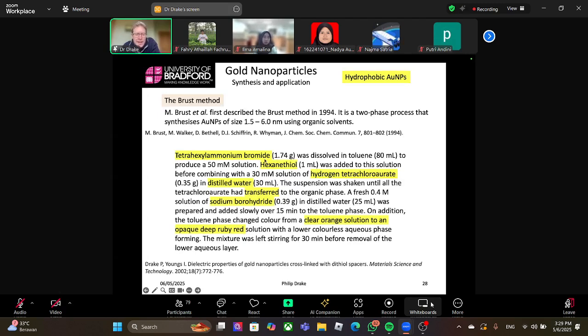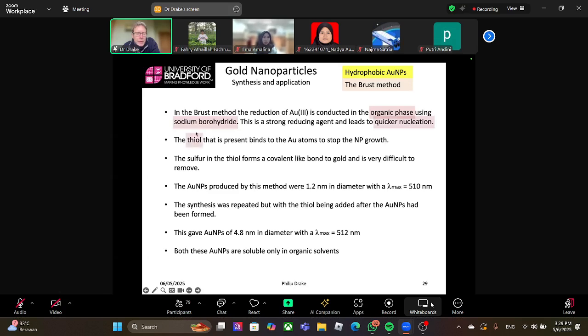The thiol, remember we added hexane thiol. The thiol is a capping agent that reacts very quickly with metallic gold and forms a very stable bond with gold. So as soon as the nanoparticles start to form with gold 0, the thiol bonds to the surface and stabilizes them. It forms like a covalent link between the gold and the sulfur, and it's very difficult to remove. Once the thiol bond forms on gold, it's very difficult to remove it. So this gives you very small nanoparticles, 1.2 nanometers, the smallest ones you can make. They have an SPR peak at about 510 nanometers.